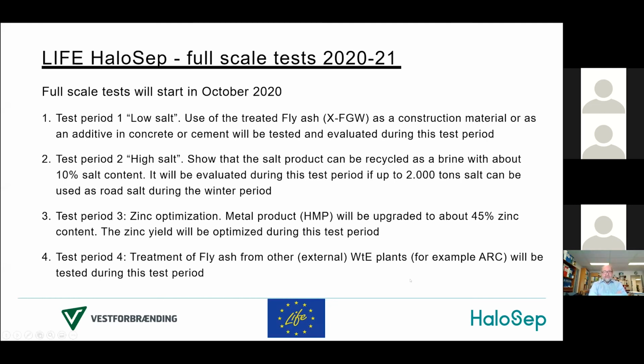Test period 3, zinc optimization. The metal product will be upgraded to at least 45% zinc, and the zinc yield will be optimized during this period. Finally, test period 4, the treatment of fly ash from other external waste-to-energy plants, for example ARC, which is the Amager waste-to-energy plant, the one with the ski slope on it, will be tested during this test period. Next slide, please.